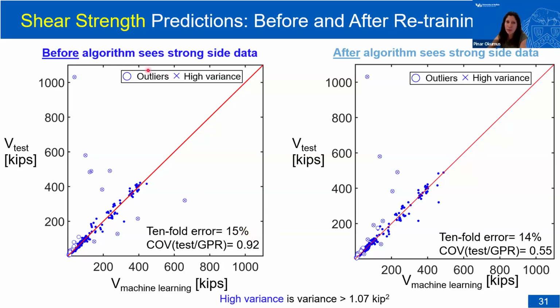So before the algorithm sees the new data is what we have on the left-hand side. You've seen that exact plot before. And then after the algorithm sees the strong side data, our error doesn't decrease much, 15 to 14% is not much, but our coefficient of variation actually decreases quite a bit. And we think that's because the issue that this algorithm has is really with really large size beams. So by adding even one larger size beam helps with the coefficient of variation.